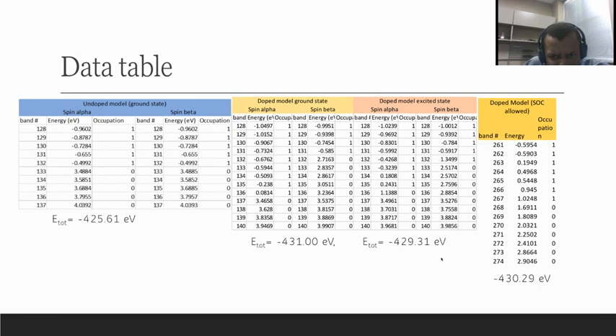So for the doped model at the ground state, the first thing that we see from the occupation column is that we have 5 extra electrons in the alpha orbital, that are spin alpha, not spin beta. So these orbitals would be attributed to the manganese, to the contribution of the manganese unpaired electrons.